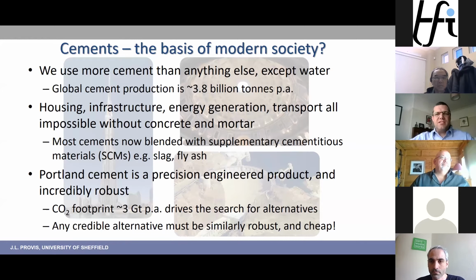And despite all of this, it's amazingly robust. Maybe because of this, it's incredibly robust. If you mix cement with, let's say, 50% less water than you really should have, it still mostly more or less works. Mix it with 50% more water than you really should have, and still, again, it more or less works. If you get the mixed proportions in your concrete wrong by surprisingly large amounts, you can still get a material that goes hard. You can use it under quite a wide range of ambient temperatures. You can use it in processes anywhere from highly controlled factory processes to slopping it into a wheelbarrow with a shovel.